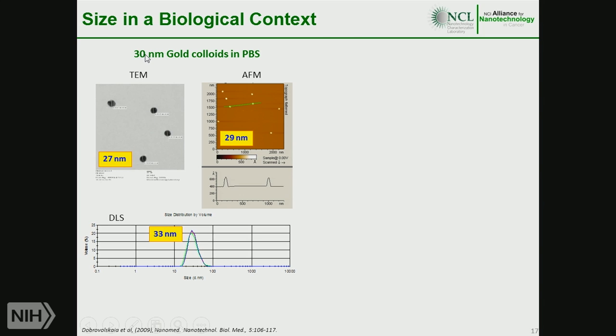Please look at this data. We are using here 30 nanometer colloidal gold nanoparticles in PBS. There is no biological matrix in this system. And we use 3 different methods to look at the particle size: transmission electron microscopy, atomic force microscopy, and dynamic light scattering. And what you see in these yellow rectangles is the measured size. So the 30 nanometers is the nominal, theoretical size, and this is what instruments measure. So about 30 nanometers, right? There is agreement between different methods.